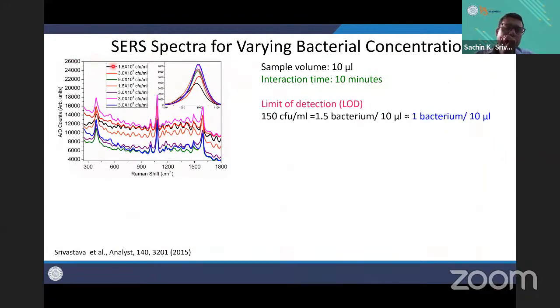So we make different concentrations of bacteria in PBS. You can see that it is like 150 cells of bacteria. This is called colony forming unit, that is cells. So 150 bacteria in 1 ml, and I am taking only 10 microliter, that is about 1.5 bacteria, roughly 1 bacterium per 10 microliter that I am going down to. What people generally do is put bacterial plates, grow them overnight, and then count the colony CFUs, and then say this is the bacteria and this is the concentration. But here we can see from the Raman spectra itself, in 10 minutes, in 10 microliter volume, what the bacterial concentrations are. So that is very effective.